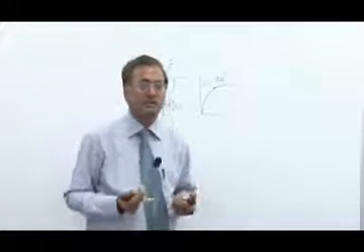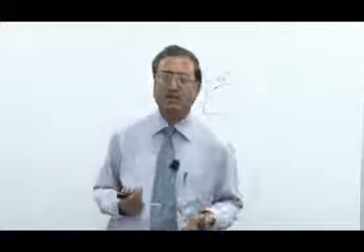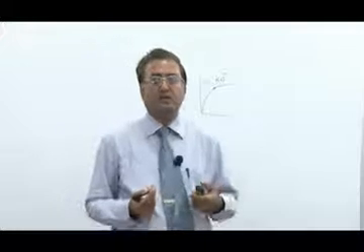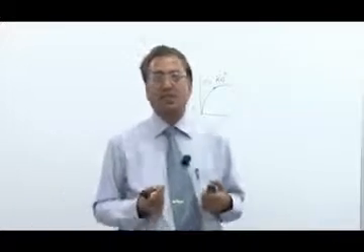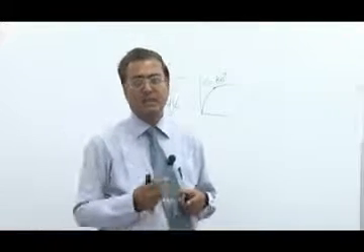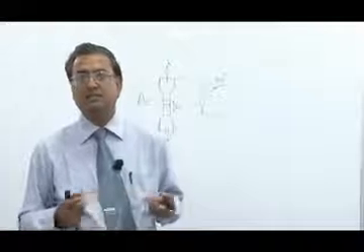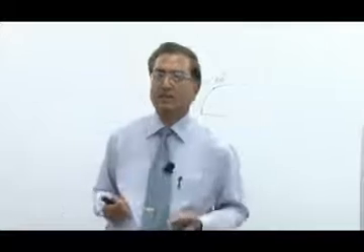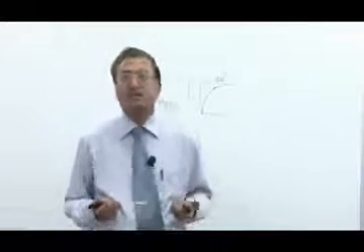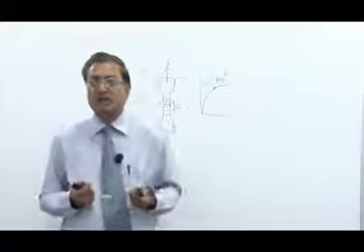So in localized necking, what happens? The neck is a narrow band with a size approximately equal to the specimen thickness, inclined at an angle of around 55 degrees, and it does not give a change in width, as plane strain deformation happens in localized necking. Looking at this figure, under this necking the decrease in specimen area with increase in strain, because of the softening, is restricted to the thickness direction only, that is dA equals the width W multiplied by the change in thickness dt, where W is the constant width of the localized neck and t is the thickness of the neck.